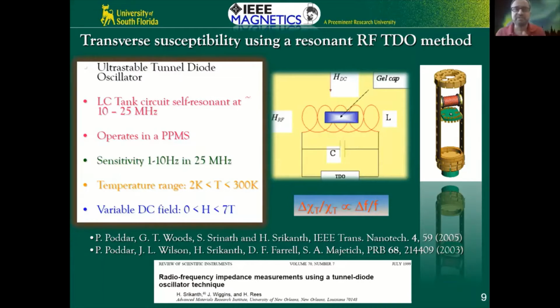So this particular technique has been extremely useful in studying anisotropy fields and other kinds of phenomena, switching and everything, with a high degree of sensitivity. We can also do this over a large temperature range using our low temperature superconducting magnet. We can apply fields up to 10 Tesla in our lab, minus 10 to 10 Tesla. So we can look at a whole range of parameter space.